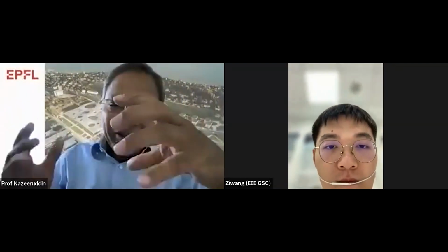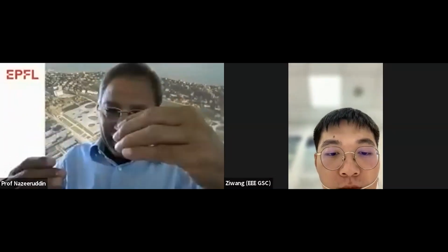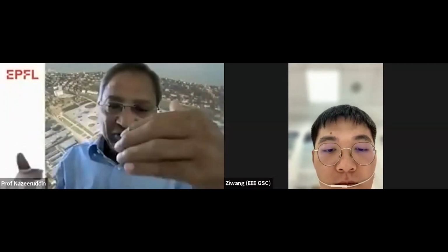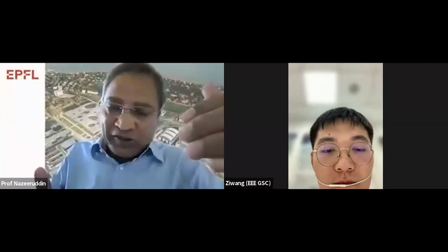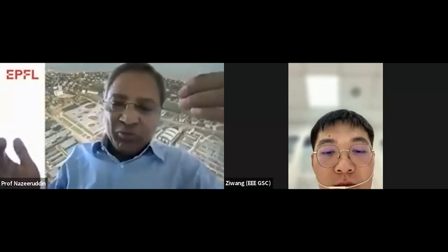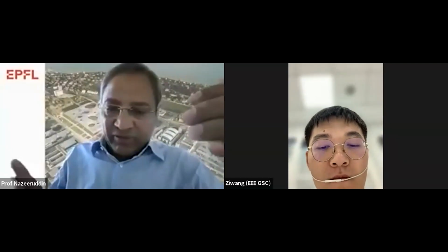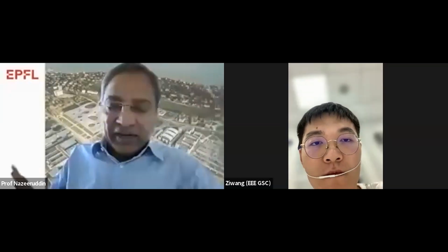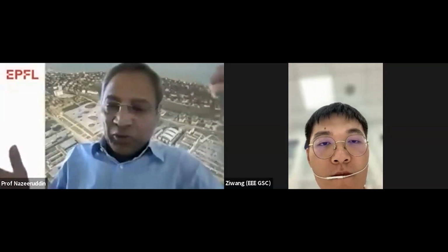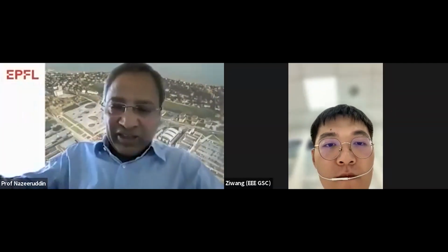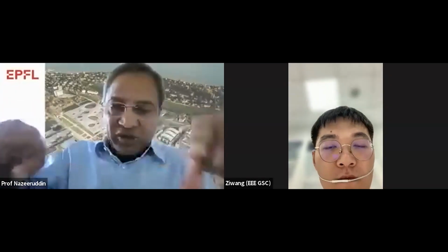However, the sublimation technique is a slow process. It can be optimized, but right now, to our knowledge, this is a slow process. For square meters, solution processing can be more suitable. That's the slot die coating method. You can have either a one-step method or two-step method, slot die coating, solution processing, high throughput, large-scale production can be feasible. Sublimation has a unique nature for deposition on top of silicon wafers, which have a pyramidal structure.